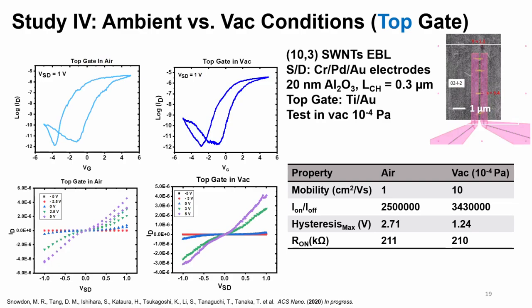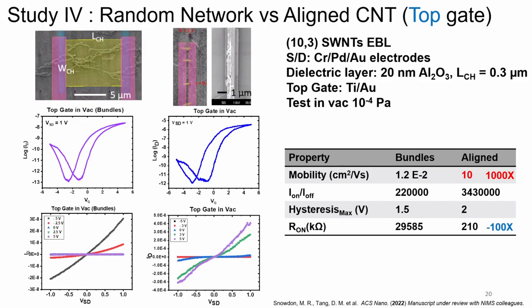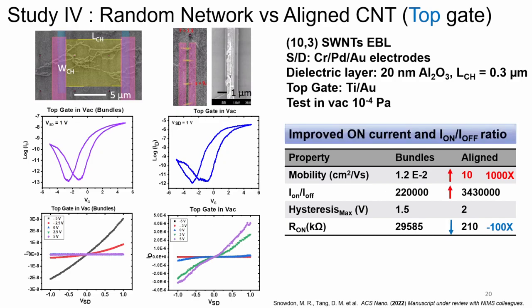When we tested the top gate in different conditions, so in air, regular atmosphere, versus vacuum, what we observe here is, again, a better mobility in vacuum conditions, a higher ion/ioff ratio, and a decrease in the hysteresis as well, which is also an important parameter. And then finally, when I compare a random network, so the bundle of carbon nanotubes, versus the aligned, which our whole purpose was to align CNTs and see if they work the best, well, they do. There's a 1,000 times increase in mobility, an increase in ion/ioff ratio, as well as a 100 times decrease in the resistance present in our system. So much improvement is observed in the alignment. And that's why we need aligned carbon nanotube FETs.